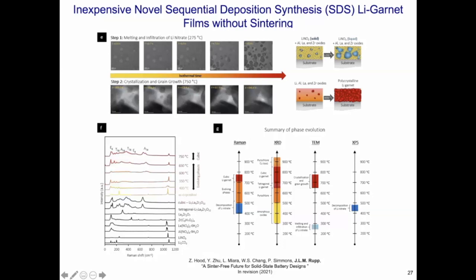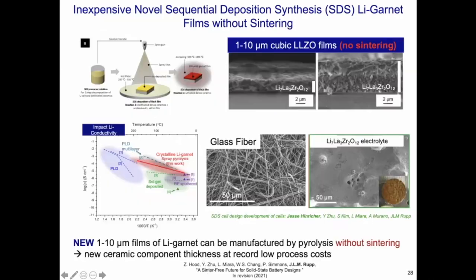And we get, at a very low temperature, these 10 micron films with the right lithium garnet cubic fast conducting phase. When you would go to very high temperatures, then we see also in the transmission electron microscopy the change from this amorphous and then actually molten-off lithium salt and then lithiated structure into actually forming grain boundaries. So that's what you see here by the shade differentiation, where you can see the progressing grain growth into the films.